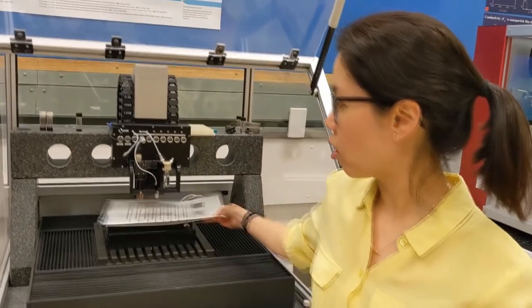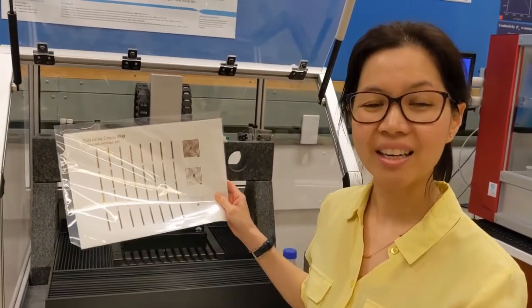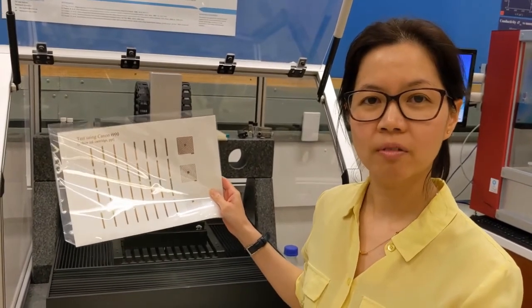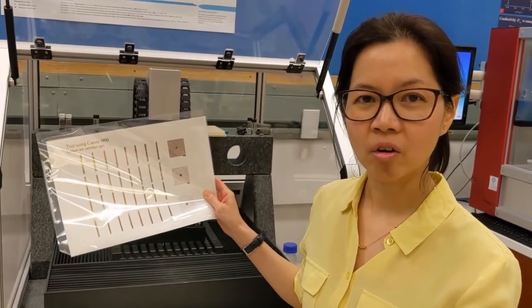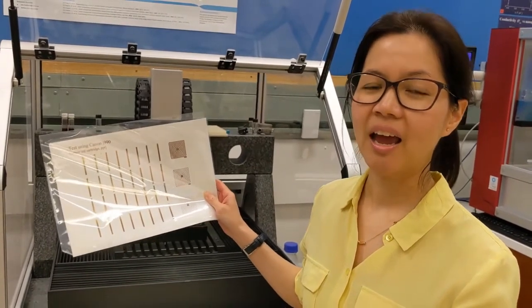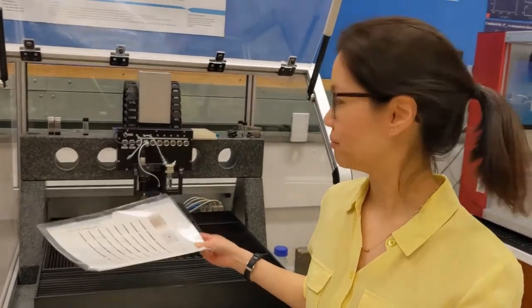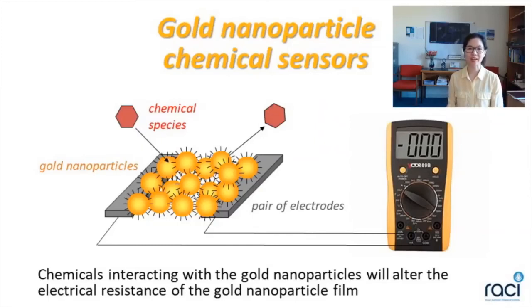You can also form thin films of gold nanoparticles by loading them up into an inkjet printer, such as the one shown behind. This inkjet printer allows you to print onto any type of surface, such as paper, glass, or plastic. When gold nanoparticle films dry, you can see they look just like a golden film. However, they behave quite differently from bulk gold because you find that these gold nanoparticles are no longer an excellent electrical conductor and they are no longer chemically inert. Instead, they show electrical resistance and they are chemically sensitive.